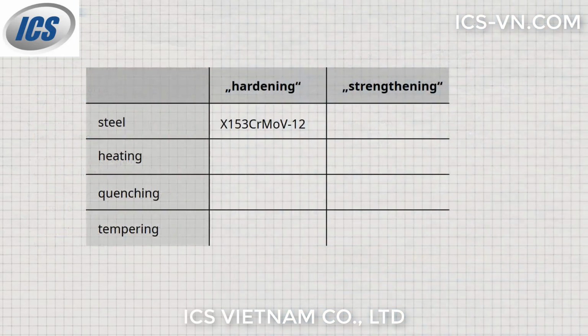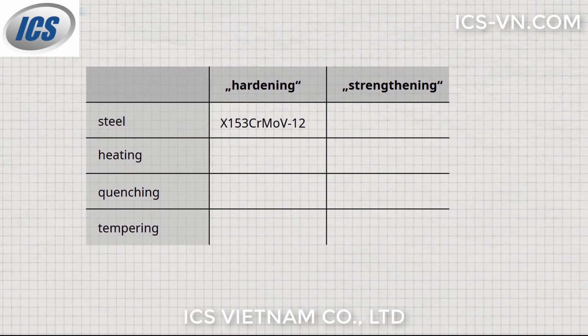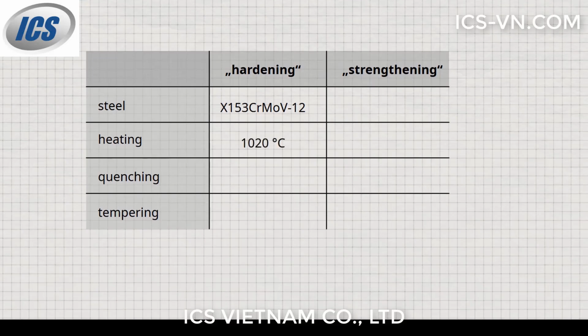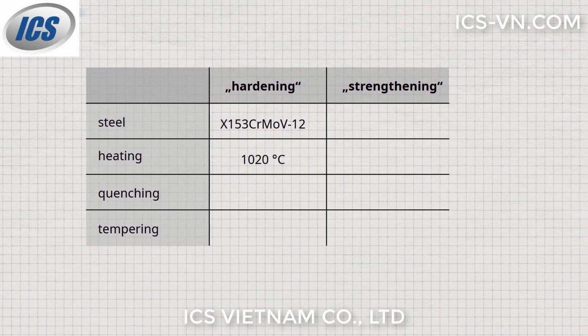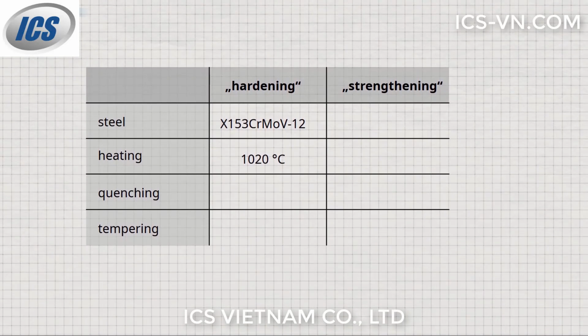A cold work steel to be hardened will serve as an example in the following. The austenitization temperature of this steel is about 1020 degrees Celsius. It is heated for approximately 25 minutes.